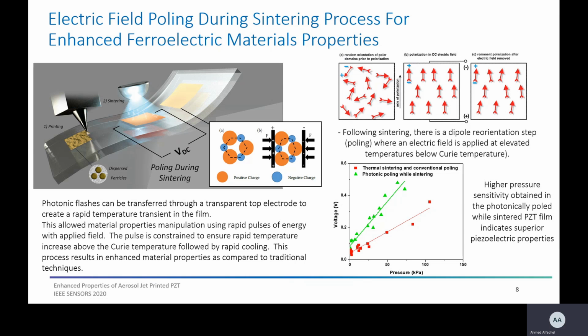Poling is an essential post-processing step for the PZT device to reorient the dipoles. For conventional ferroelectric materials poling, an electric field is applied across the films at elevated temperatures below the Curie temperature to increase dipole mobility. A possible approach with the rapid sintering in this work is poling during the sintering process without applying an extra annealing step. Repetitive pulsing of the photonic lamp provides the appropriate total energy and pulse profile to anneal the material, facilitate the dipole reorientation, and enhance the piezoelectric properties.